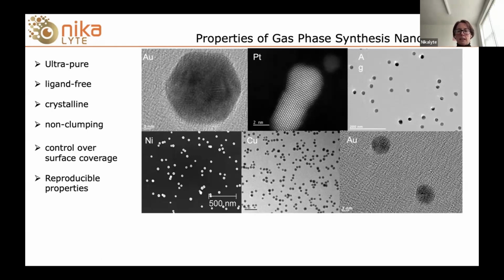The other feature, which is really key, and I want to mention at this point, is that we have really reproducible results. Because we have such good control over the size, the shape, the structure, the loading, it's possible to reproduce these coatings each time with the instrument. As long as you enter the same conditions at the start, you'll end up with the same coatings, which is really important and is not necessarily the case for other methods. Certainly from talking to researchers working in chemical synthesis of nanomaterials, I know it can be quite challenging to recreate reactions and generate nanoparticles with the same properties.